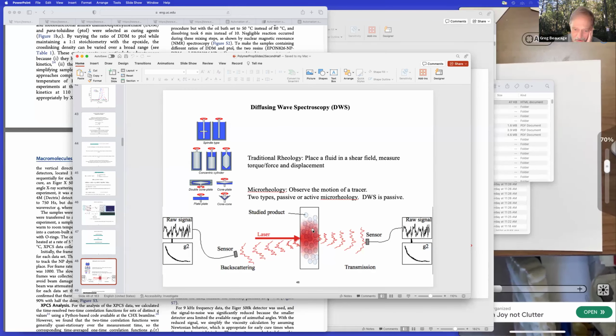So you know what the diffusion coefficient would be, what you don't know. So the gamma is going to be 6 pi times the RH, hydrodynamic radius, which you know here because they're monodispersed, and then times the viscosity, right? So you can get the viscosity out of this if the viscosity is changing with time, like in a curing system. So that's what they're doing.